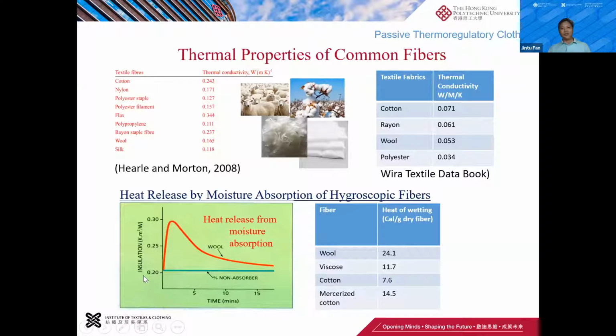Like wool fiber is actually a very smart fiber, because as the fiber absorbs moisture, which could be from our human body, or as when we walk from a relatively dry condition to a humid condition, it absorbs moisture and releases a lot of heat. But this is transient, over a short period of time. Like this graph shows, perhaps within 5 minutes, the effective insulation can increase because the wool releases heat. But polyester or nylon are non-absorbent fibers. They do not have this kind of property.